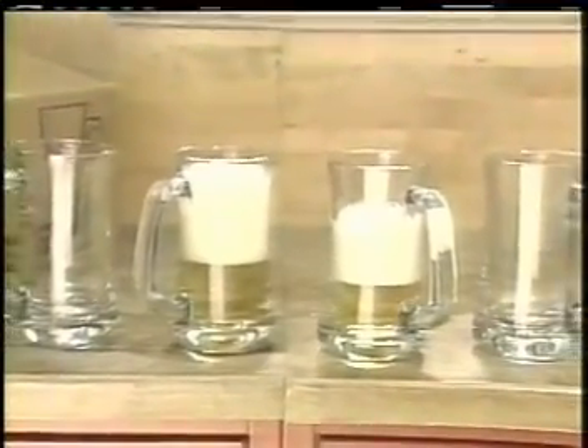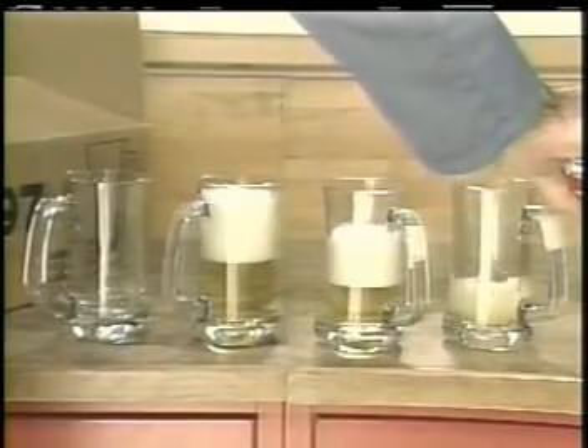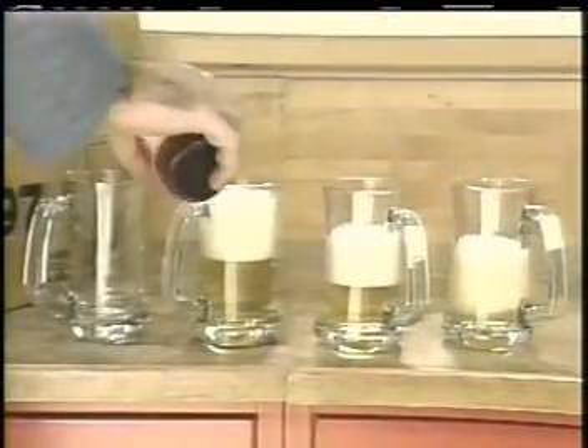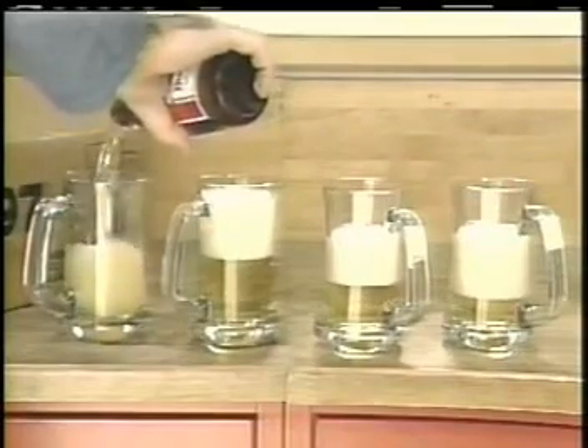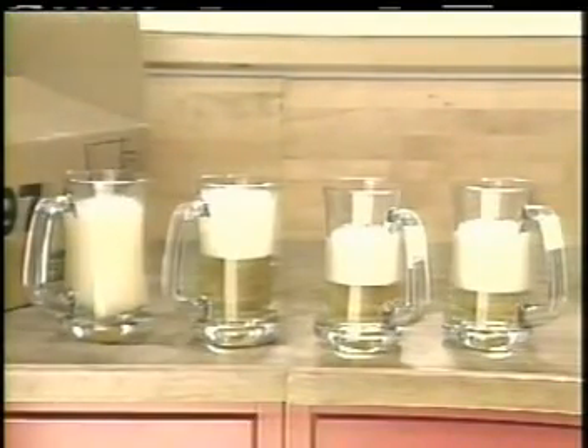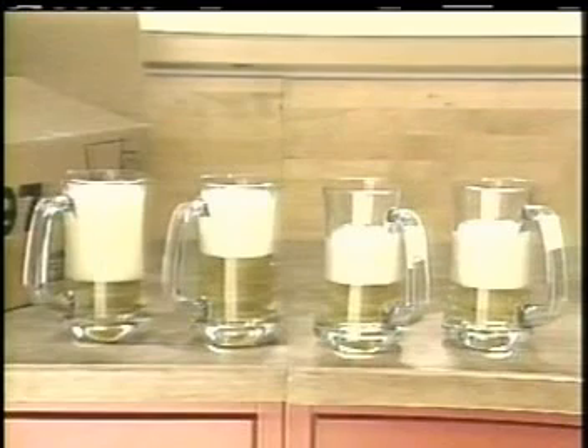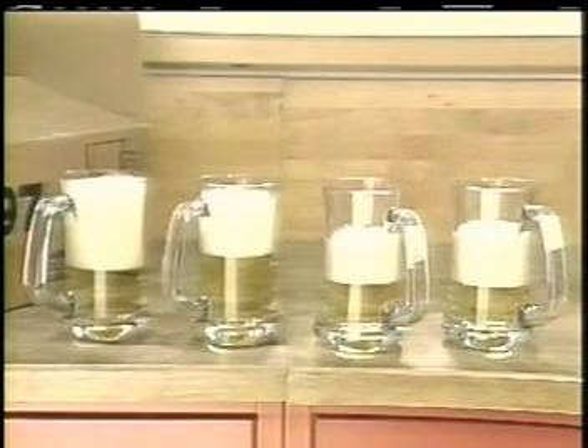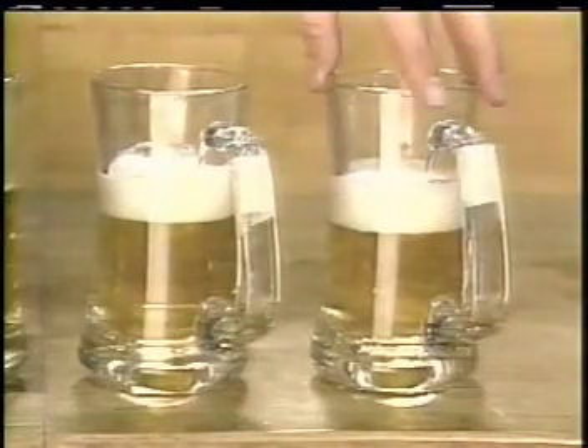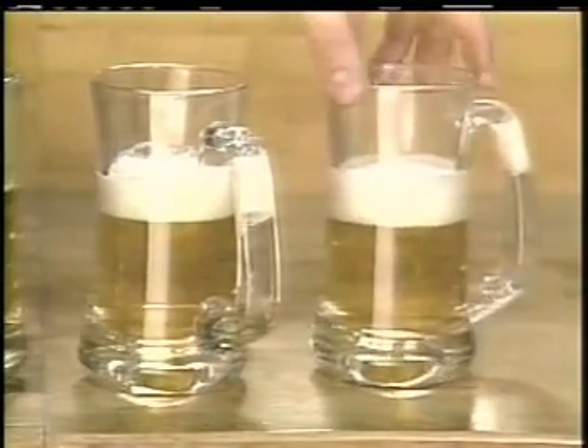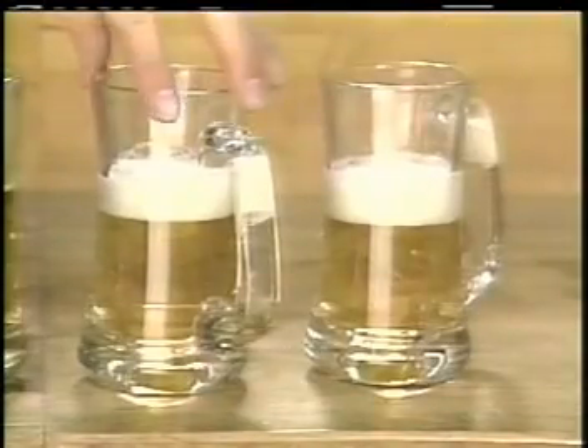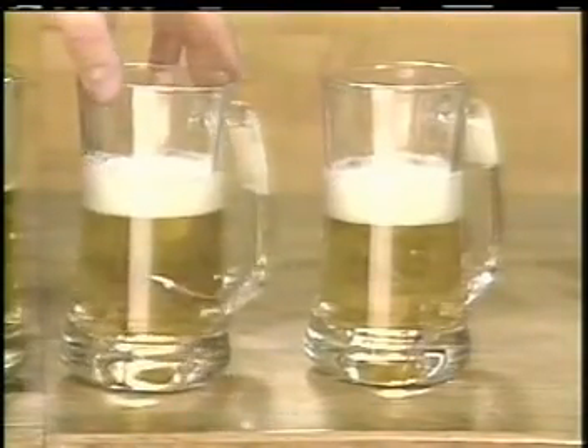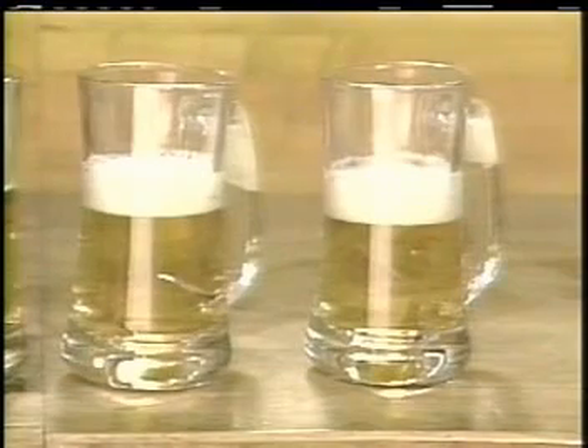Remember, according to our formula, for every degree difference between the temperature of the warm glass and the temperature of the cold beer, there is 25 pounds of stress per square inch on the surface of the mug, which figures out to a stress in excess of 2,000 pounds per square inch. A lot of stress. As you can see, the glasses that were damaged were not able to withstand the thermal shock, because the nicks and scratches serve to concentrate the stresses on the surface of the glass until they reach the breaking point.